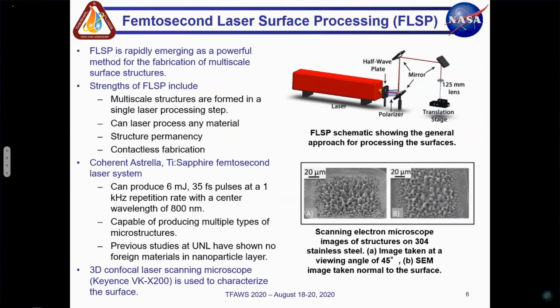We're able to laser process almost any material. We've done anything from stainless steel to Inconel to titanium and even glass. These structures are permanent, they're not going to change over time, and we're able to make these without having any kind of contact with the surface itself. The laser that we're using right now is a Coherent Astrella titanium sapphire femtosecond laser. Right now it's capable of producing 6 millijoules, 35 femtosecond pulses with a 1 kilohertz repetition rate, with a wavelength of about 800 nanometers.